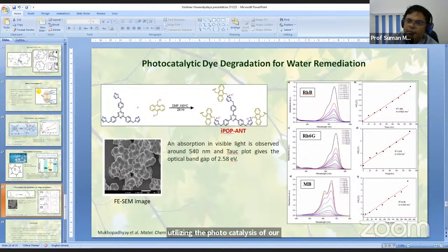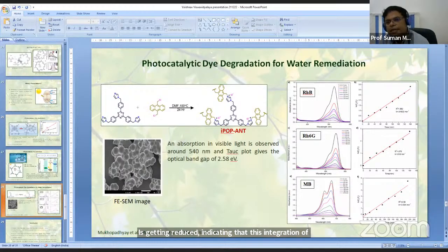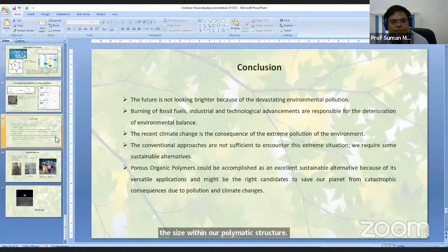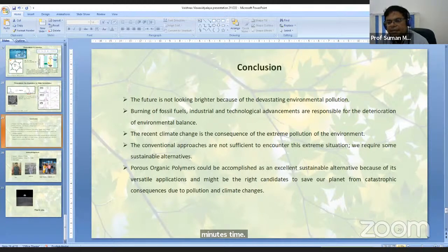And you can see that with the time, the specific signature peak for these dyes, rhodamine B, rhodamine 6G, and methylene blue, is getting reduced, indicating the disintegration of these dyes by our polymeric structure. So it can disintegrate up to 97% of the dye within few minutes time. So to conclude, what we can say is that